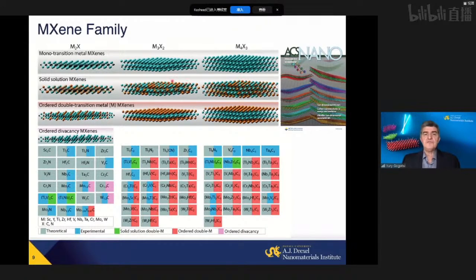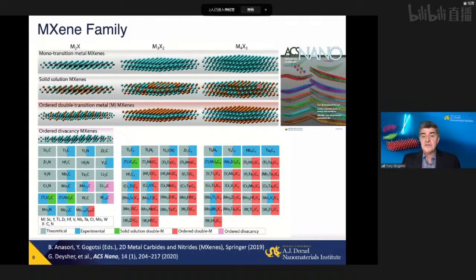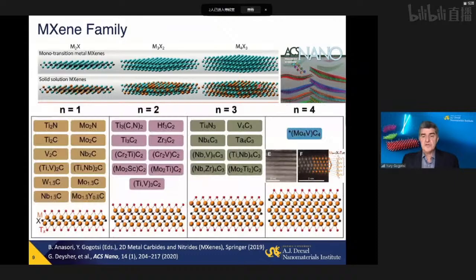And to take it further, we can mix different atoms in solid solutions, in both the X layer, carbon or nitride, but also in the M layer. For example, you can imagine a catalytic material with, say, a molybdenum or tungsten atom surrounded by titanium atoms, a kind of single atom catalyst. And you can pretty much create an infinite number of compositions. But the research goes on.